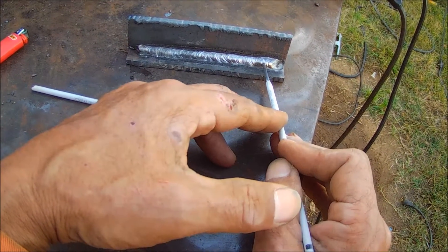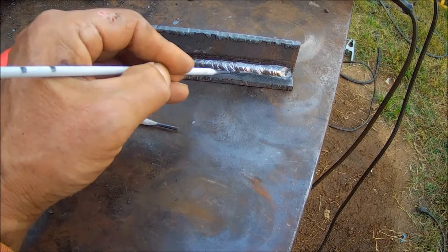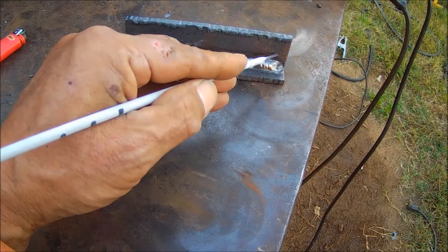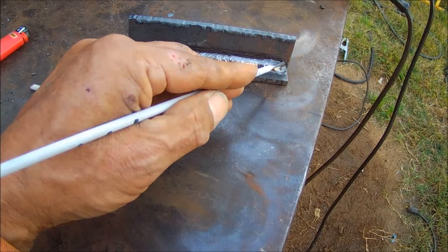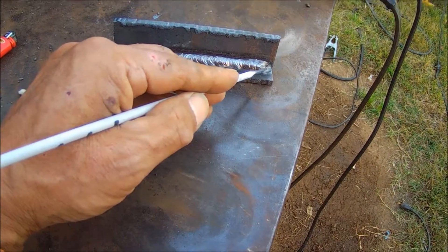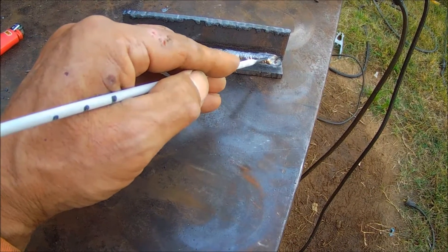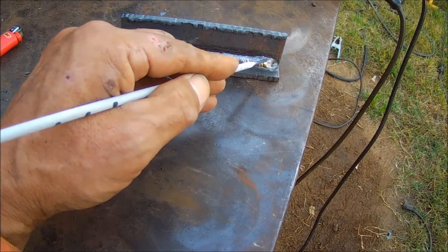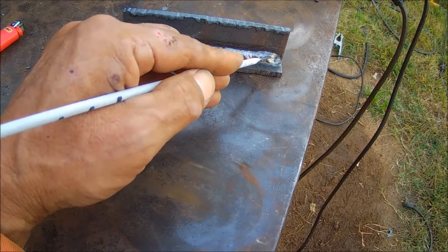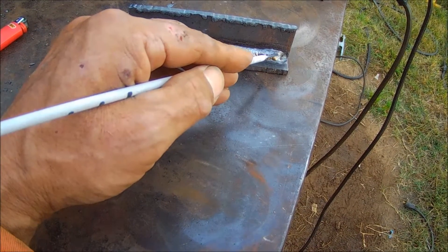I mean, I'm not 100% on it, so don't take this to the bank. But you've got a large bow out here. But as you get towards the end of that piece of metal, that magnetic field gets compressed. And the arc is going to want to go back down here. It's going to want to go back downhill instead of coming up behind you. So what you need to do is when you see that starting to, you'll see it flare. It's going to start looking funny to you. You know, it'll get bright.